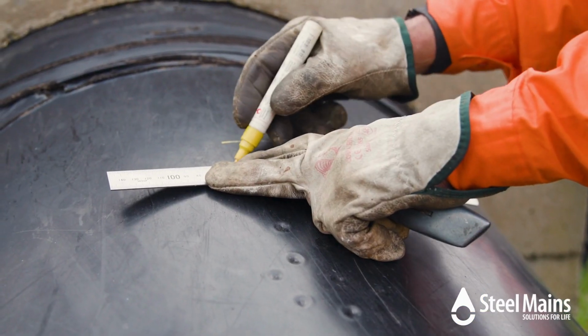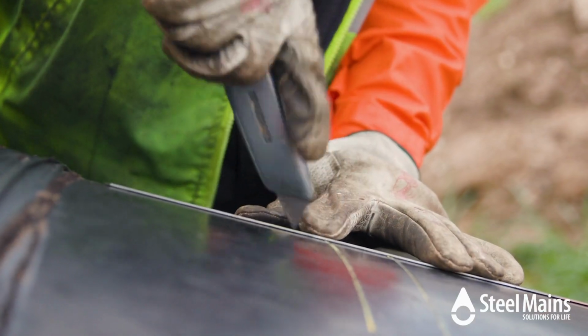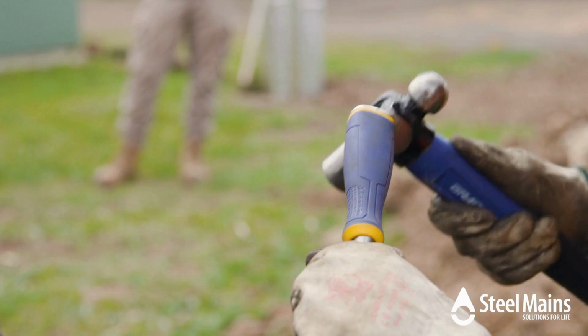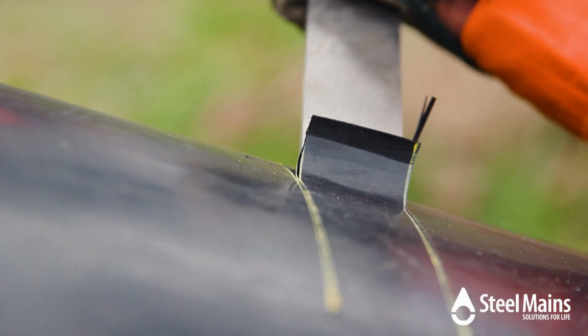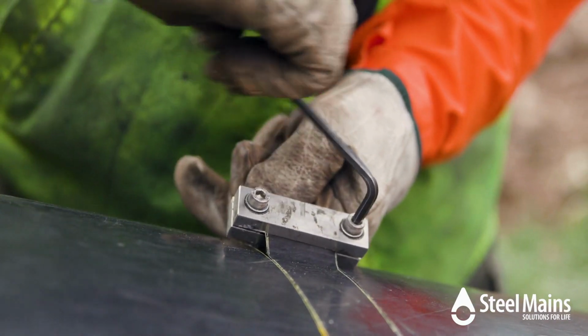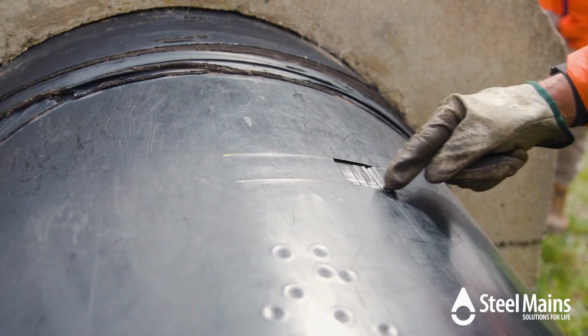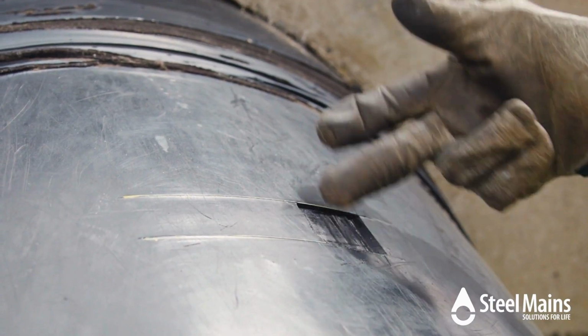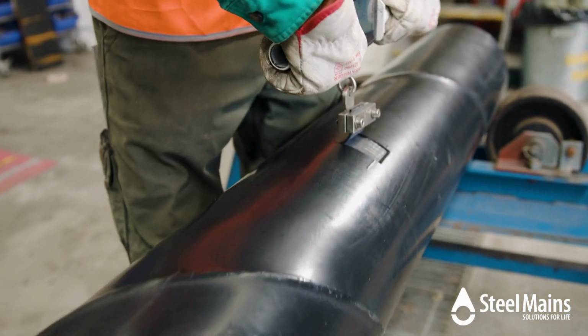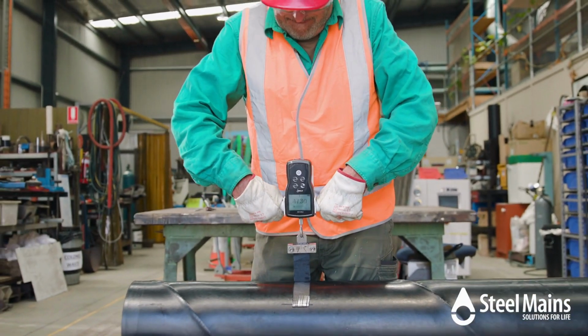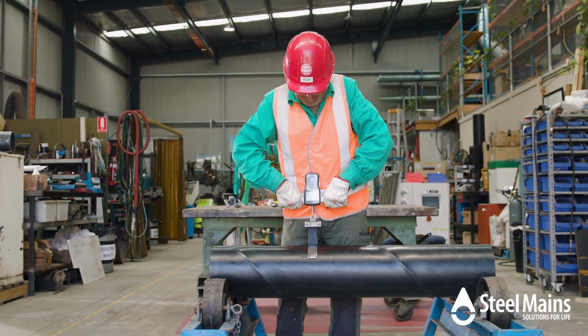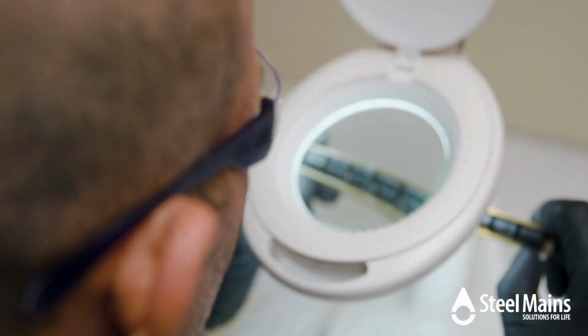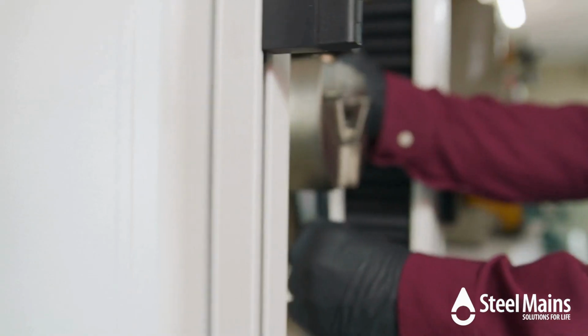We then assess adhesion, the bond between coating and steel. Strong adhesion confirms that aging has not compromised performance and that the coating cannot be displaced by shear forces from surrounding soils. As in previous tests, adhesion is so strong that a standard test sample cannot be separated for quantifiable measurement. Adhesion remains exceptional. Samples are sent for laboratory analysis.